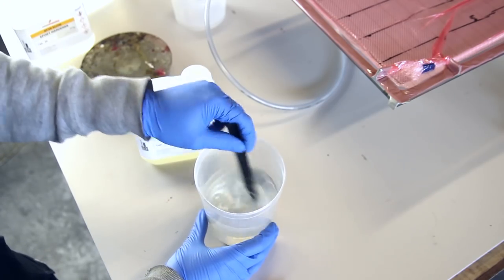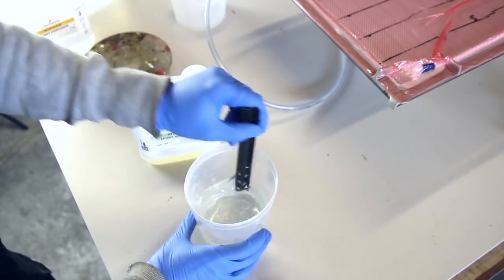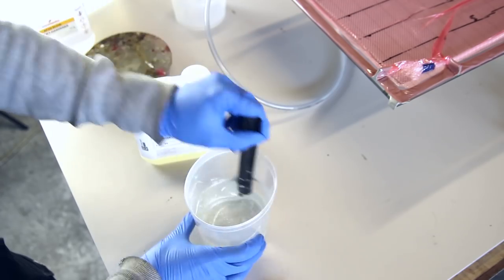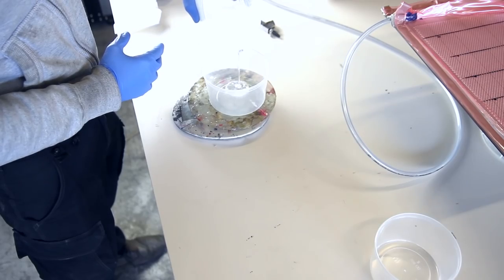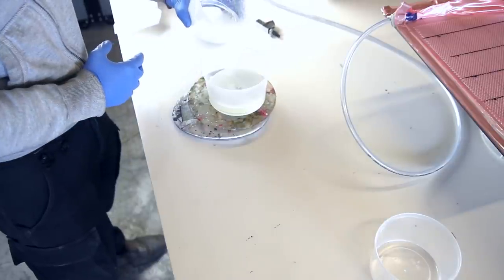Another lesson in making carbon fiber pieces with resin infusion is never infuse a part if you have a leak. I always like to do the vacuum at night, and when I come back and I still have a full vacuum, then I know that the part is fully sealed.